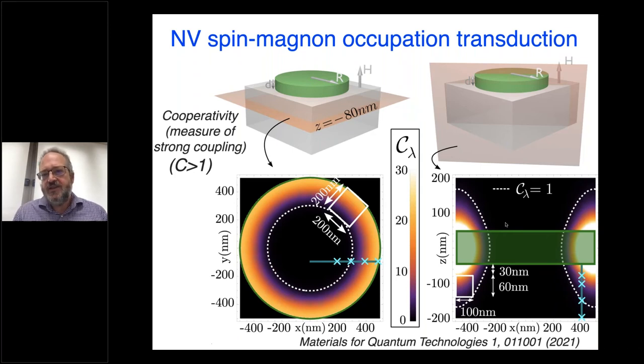This here is at a distance about 80 nanometers below the surface of the diamond, so it's a slice below the disk. And on the right is a slice through the disk and the material underneath. The green region is, in fact, the disk itself. And you can see the cooperativity can get quite high, in excess of 30 for regions that are reasonable.